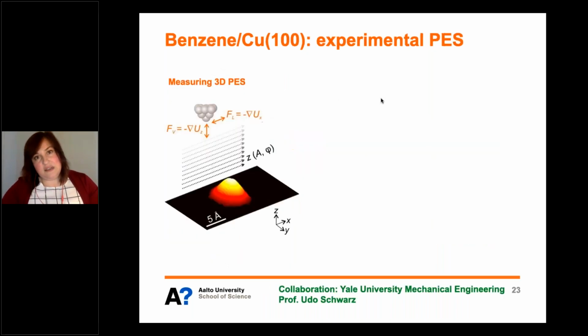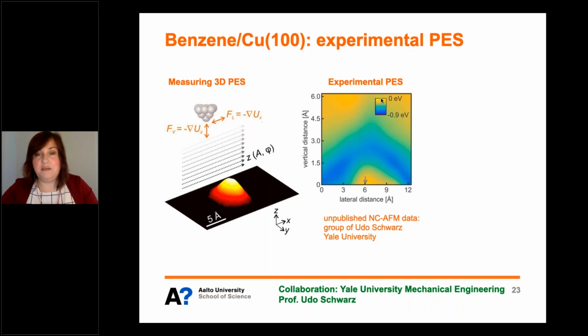Now, we were very excited about computing all these potential energy surfaces, and we were even more excited when we learned somebody was experimentally measuring it. So this is a collaboration with Yale University, where the group of Professor Udo Schwarz put a benzene on copper 100, and they used the AFM tip to do these horizontal passes above the molecule with increasing tip distance. And this is how they extracted forces and energies acting on the tip and built up an experimental PES above this molecule. So you can see the molecule is roughly in the center, and you have this conical shape, the blue conical shape, and the maximum of interactions about minus 0.9 eV, and the rest is going up to 0 in vacuum.